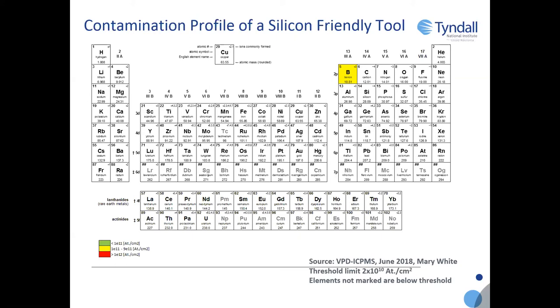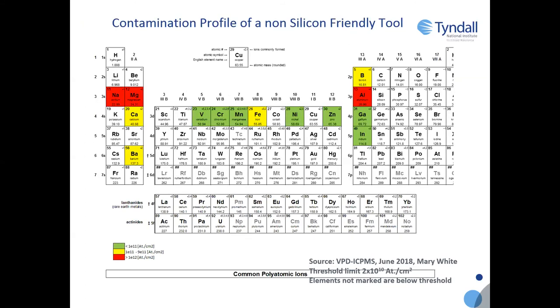And the periodic table here, everything that's white, the levels are below our threshold, which is 2 by 10 to the 10 atoms per centimeter squared. So on this wafer, the only thing that we detected in that range was boron. Now, most of our wafers, test wafers particularly, would be P-type silicon, so they're doped with boron, so you would expect to see boron. But overall, it's clean. It's silicon-friendly. When we say silicon-friendly, we mean the wafer could go into our silicon CMOS fab and not cause a contamination issue.